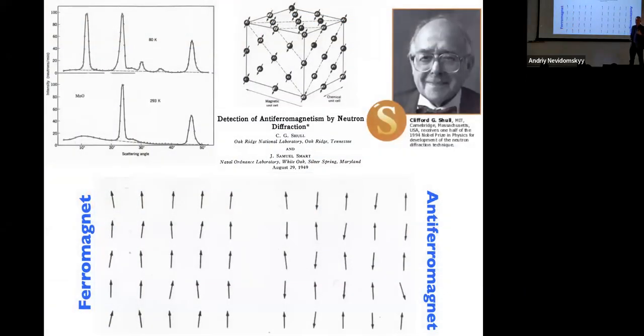So why was antiferromagnetism really only discovered in 1949? It was actually postulated before that, but this was the discovery paper, Shull and Smart from 1949 at Oak Ridge, detection of antiferromagnetism by neutron diffraction. And these are two neutron diffraction patterns that they observed. Basically, it's a powder diffraction measurement, a very simple measurement, at liquid nitrogen temperatures and at room temperature. And they see some extra diffraction peaks at low temperatures. Those extra diffraction peaks were from the manganese dipole magnetic moments that were arranged in this antiferromagnetic structure of manganese oxide, but only below its phase transition temperature.